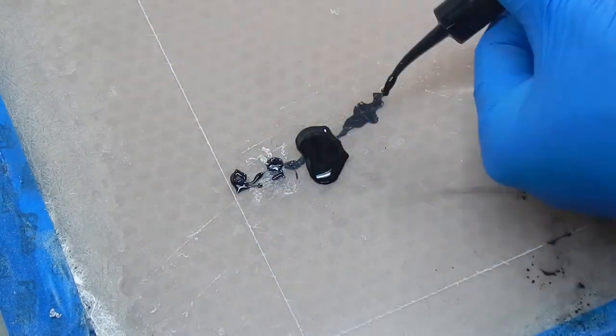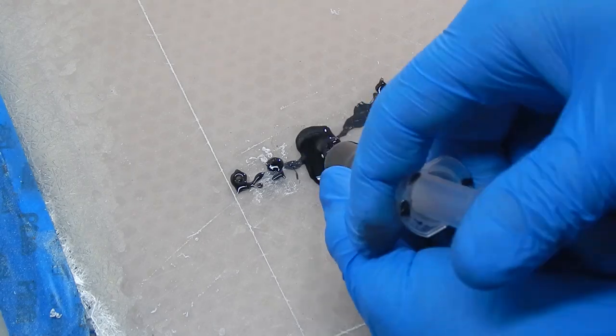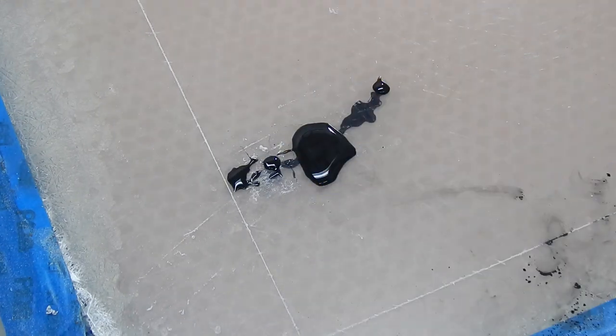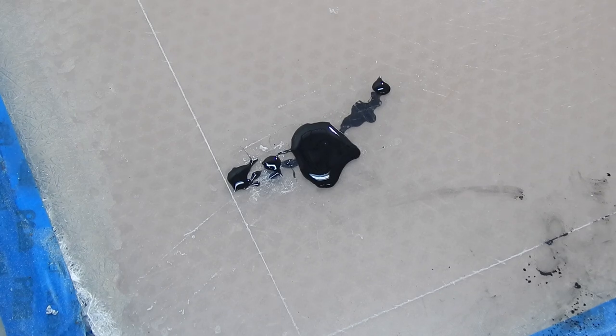But here you can see it filling that void traveling from, and need another hole. And I'm getting a lot of it into the cells there. But it does go through and it does fill the void area because the resin can flow through from one end to the other.